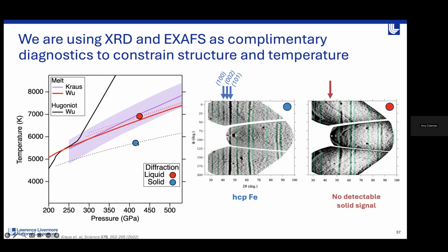In the compression regime just below the melt curve, we're seeing very strong signal from HCP iron, and it's really unambiguously HCP iron - there's no overlapping peaks from anything else. Our calibrant peaks, highlighted in green on these diffraction patterns, are quite far from our experimental peaks, and we're seeing nicely the first full three peaks of the HCP structure. So it's really quite unambiguous what's going on there.